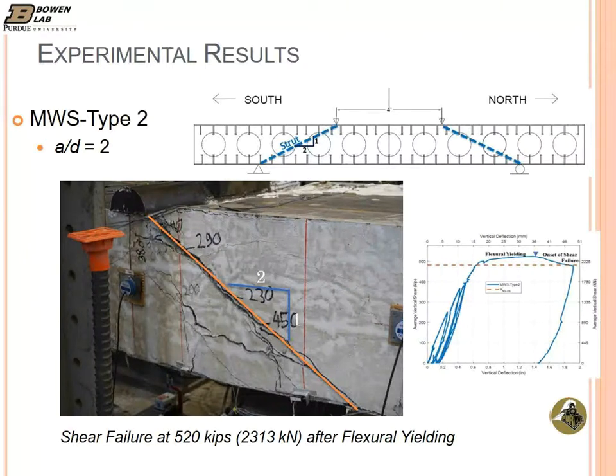And this is a picture from during the failure of the specimen. You also see a difference from the first specimen. Last time we had a 45-degree angle compression strut failure. This time it was more of a crack extending from the load point to the support with a slope of 2 to 1. And that was also different from the first specimen because we didn't have the inner plates in place, so it was a different stress mechanism that was forming.